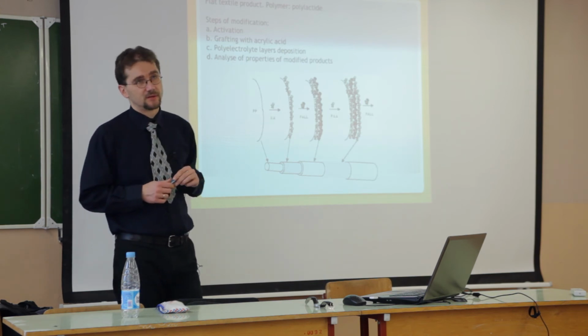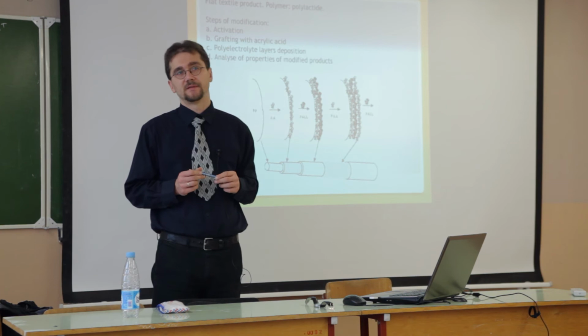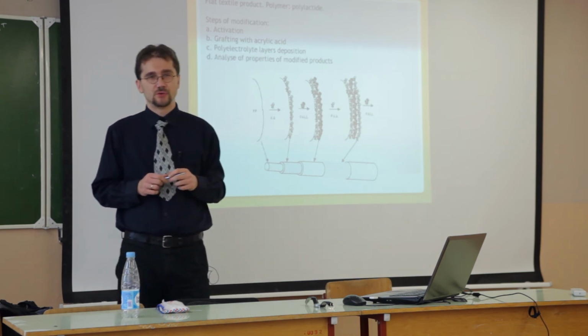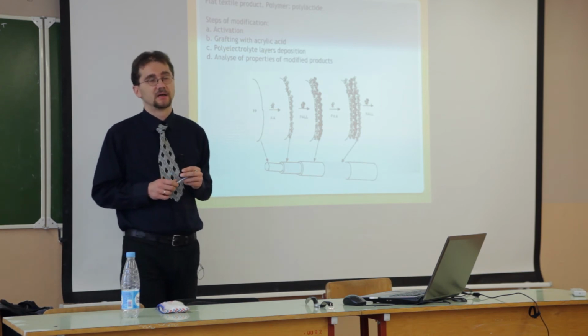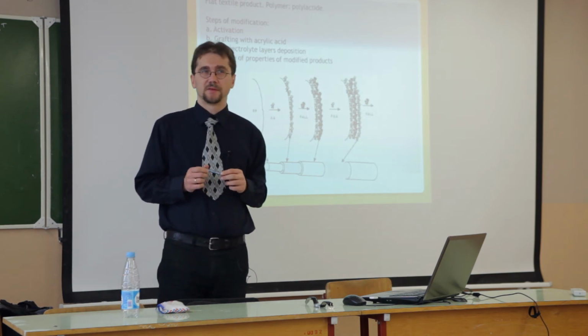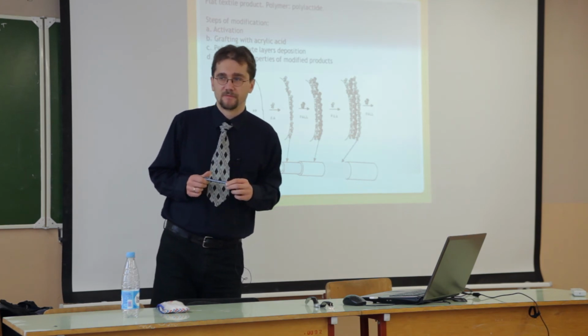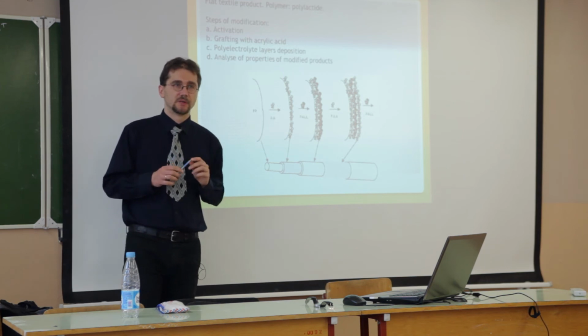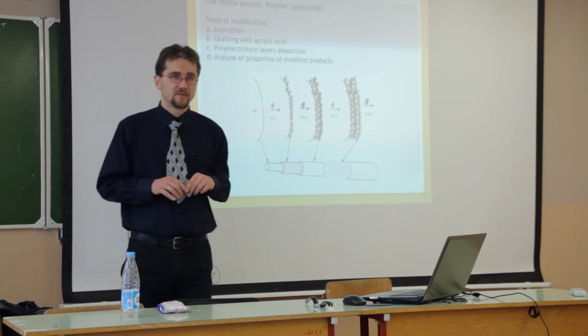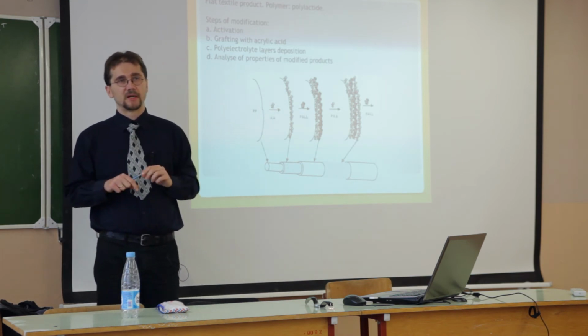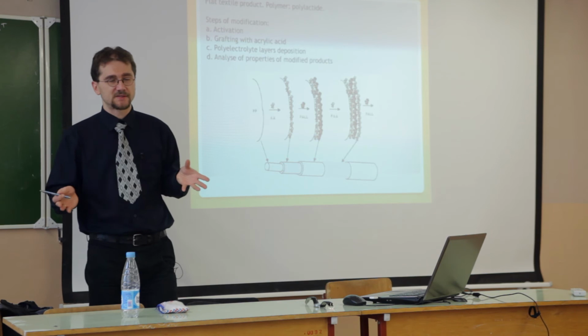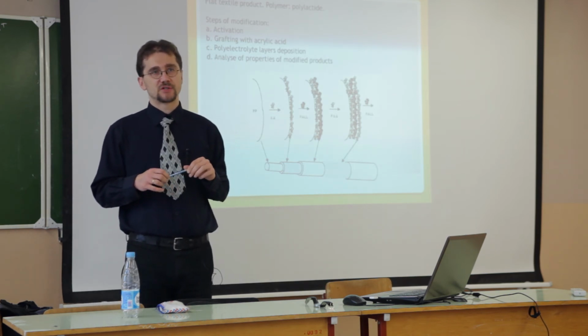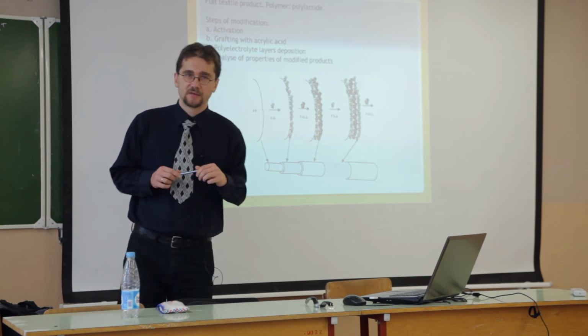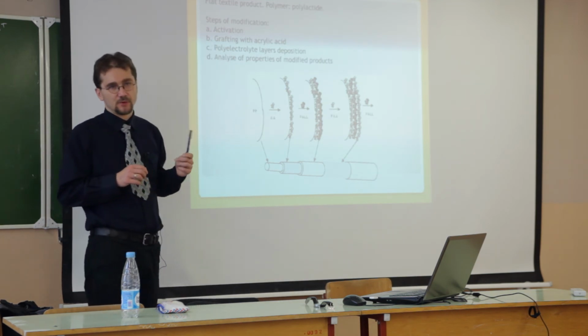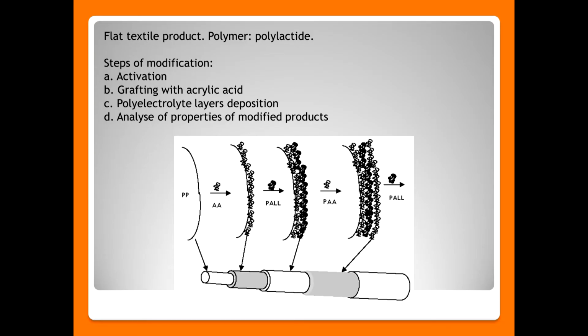This technique is known since about 20, maybe 25 years. Firstly, it was used for modification of glass, mica, gold, silver, platinum, etc. I found maybe 10 years ago some application of the layer-by-layer technique for one separate cotton fiber, but real modification of a textile product was initialized in my unit, in my division. So we were first in the world to apply this technique for modification of real flat textile material, not a separate fiber.